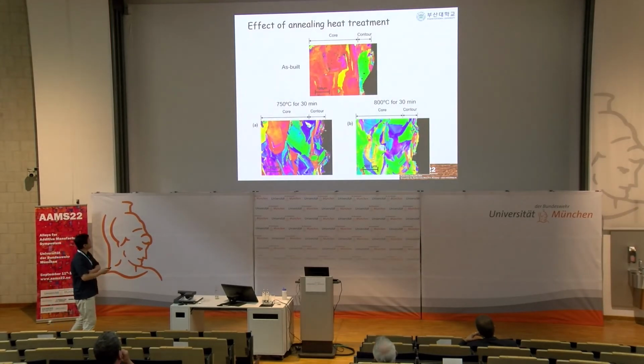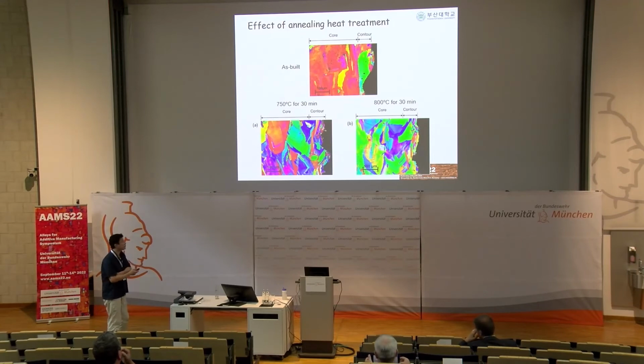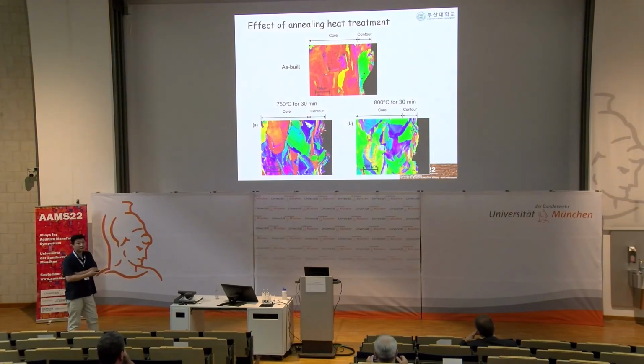This is to summarize the result, where we can see the clear trend that in every direction we are increasing the yield strength and the tensile strength, and decreasing the maximum elongation by decreasing the feature size. And so to figure out what is the real origin of this effect, we did heat treatment. We used 2 different heat treatment conditions.